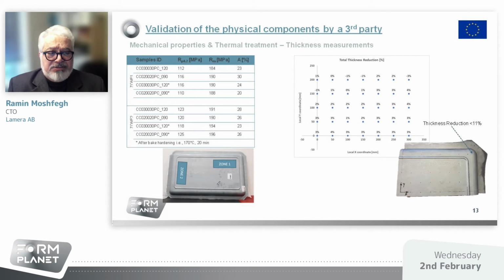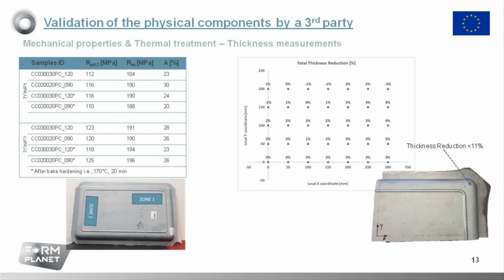We made an experimental procedure for thickness reduction, and we could see if they take the material directly from different parts of the formed product and make a measurement if the material loses performance basically after the forming or not. And that showed that's good enough, actually.